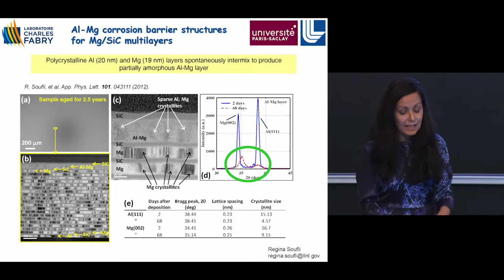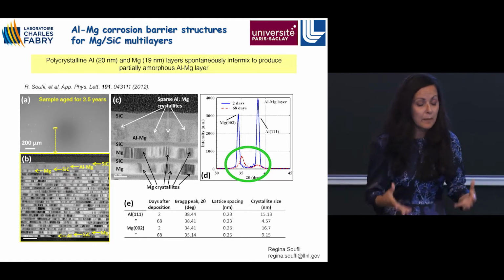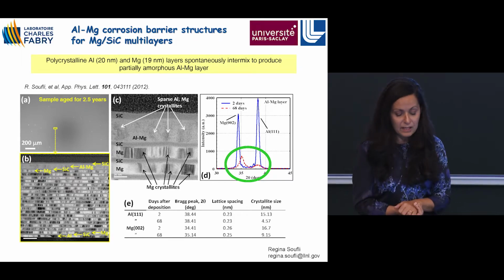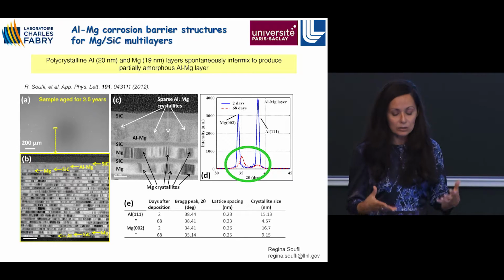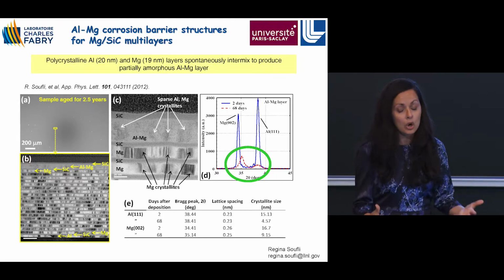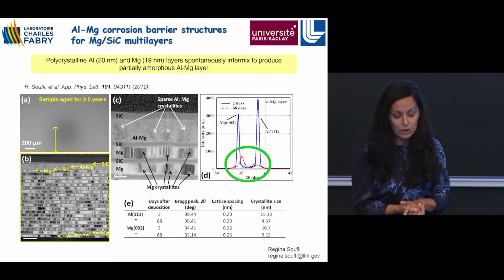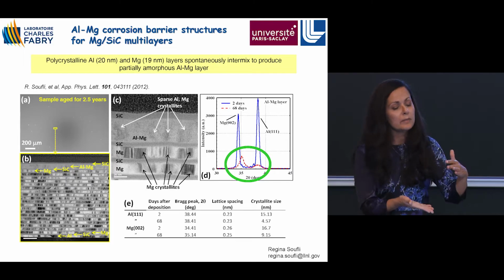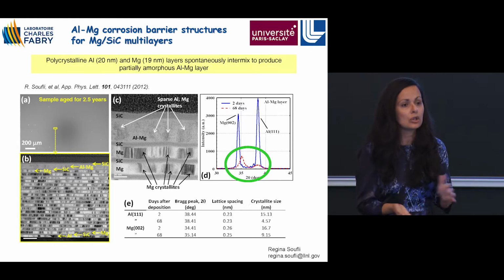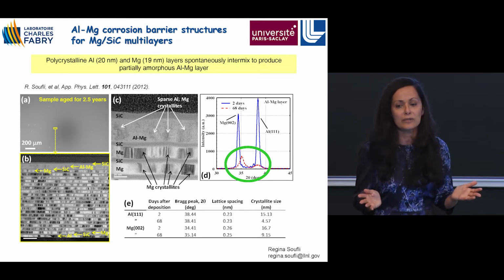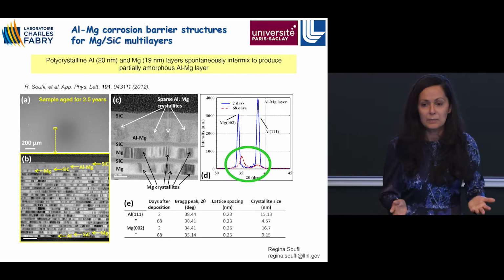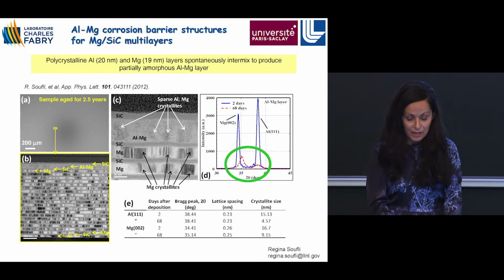So we decided to try and find something that can protect from this catastrophic effect. Basically, you need a barrier that protects from corrosion while maintaining high reflectivity and all the other good properties of this multilayer. Putting a film that is extra thick on top of the multilayer is not going to help because you're going to lose all of your reflectivity. So you solve the corrosion, but you don't have a good multilayer anymore.